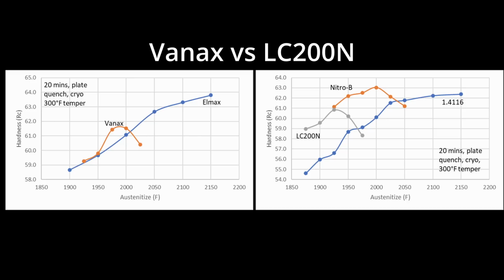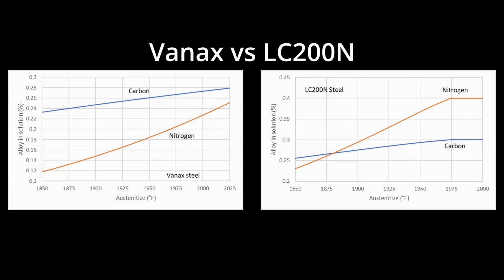So I don't know if it gets a half point harder than LC200N because of all the extra particles in there, or because it has a higher ratio of carbon and nitrogen, or some combination of those two. But again, we've got a high nitrogen steel with high corrosion resistance, and it reaches 61, maybe 62, maybe.